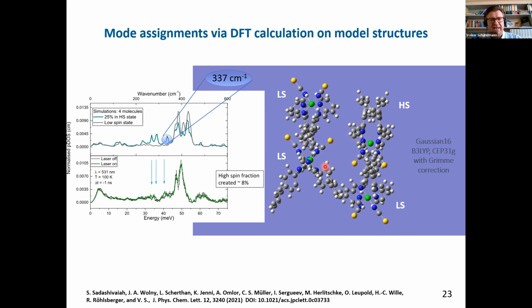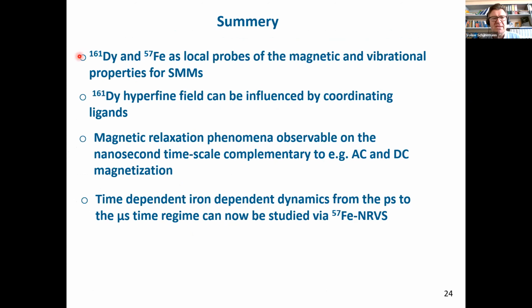I've been told I have 25 minutes, so I would like to come to the summary. And I must say dysprosium and iron are very nice local probes for both magnetic and vibrational properties for SMMs. You can do chemical spectroscopy with dysprosium by analyzing the hyperfine field, which can be influenced by coordinating ligands. One can observe magnetic relaxation phenomena on the nanosecond time scale, and at the same time measure the dynamics, the vibrations. And also I gave you, perhaps interesting for future applications also at APS, a clue what we did with the